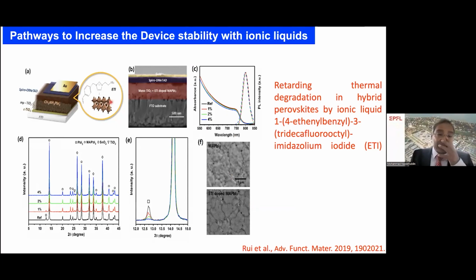So here is the strategy. We are bringing extra ions. That's an ionic liquid. Now we know this from our previous studies, the fluorine substitution protects your perovskite. Can we substitute fluoride groups? If you look at this ETI molecule, that's the imidazolium-containing molecule, which has the fluorine-substituted alkyl chain. So this is the ionic liquid we have selected, and by using this ionic liquid, let me just go to panel E, where it's an expanded version.